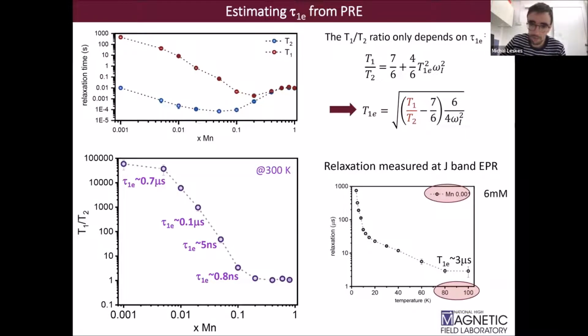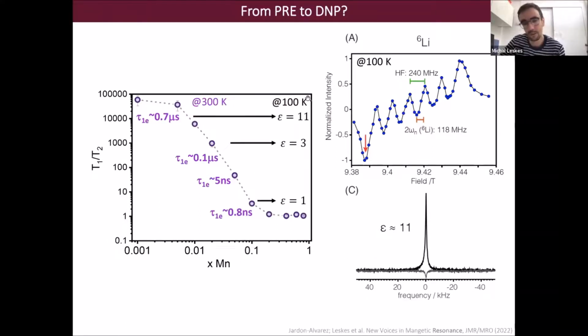And then the next question that we were hoping to answer is, can we with this predict DNP enhancement? So we took some of these samples and put them in our DNP spectrometer at 100 Kelvin and tried to hyperpolarize the lithium-6 NMR signal. And fair enough, we see that at this low concentration, we get a decent enhancement of 11. And as we increase the concentration, with decreasing electron relaxation time, we also decrease the DNP enhancement. So this, at least qualitatively, is consistent and is what we would expect, right?